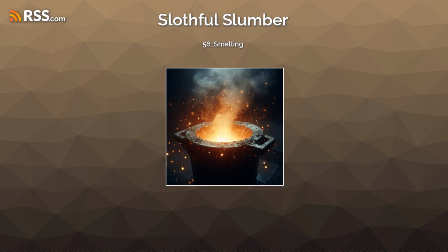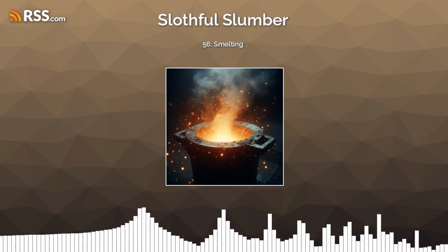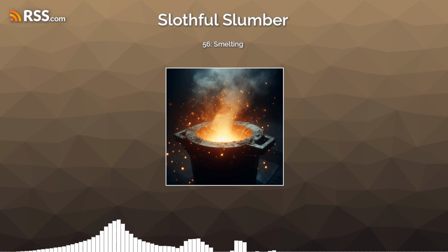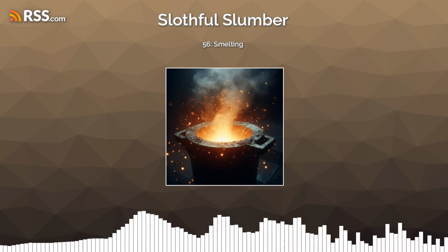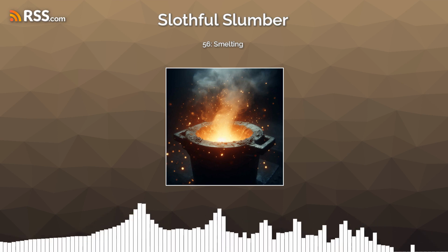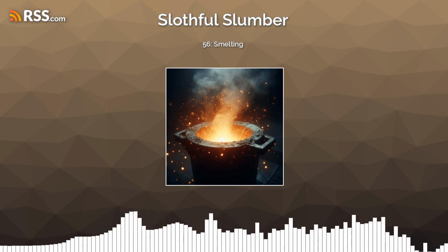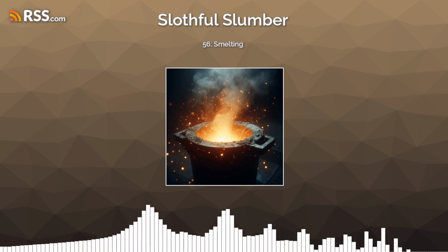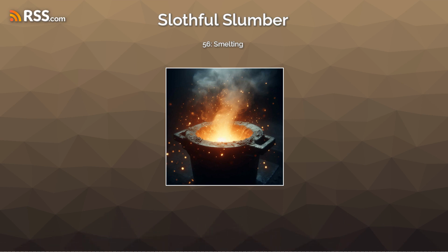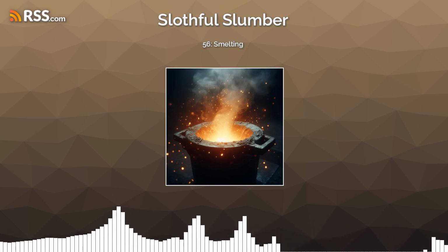Examples: iron oxide becomes metallic iron at roughly 1,250 degrees Celsius, 2,282 degrees Fahrenheit, almost 300 degrees below iron's melting point of 1,538 degrees Celsius, 2,800 degrees Fahrenheit.